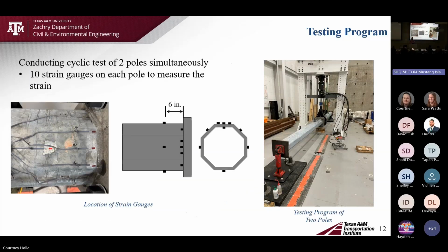And you can see here a little bit more detail on our test setup, how we're not just investigating what kind of stresses we are getting in the pole, but we're also focusing on how the location within the pole affects the stresses, whether it be at the bend or in the middle of one of the slats of the pole. And so currently we're just testing poles, getting an idea of their fatigue life with our test setup, but eventually we're going to put one of our fail-safe system poles into the test setup and put our theory into practice, and hopefully see that there's no fatigue issues there.